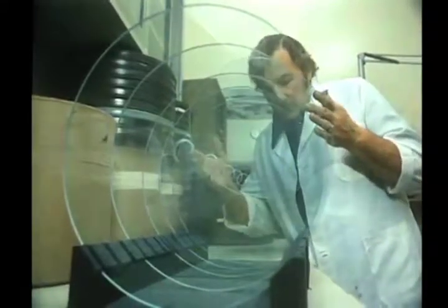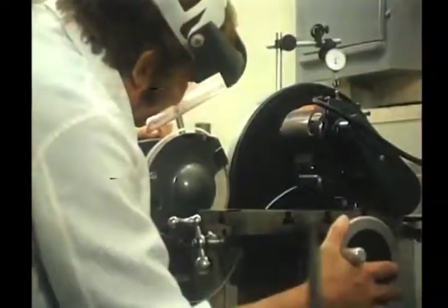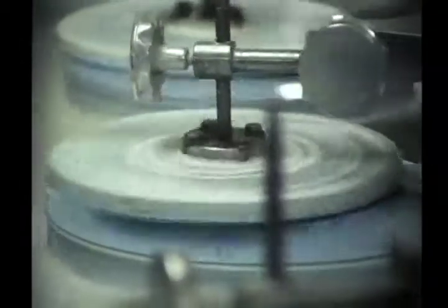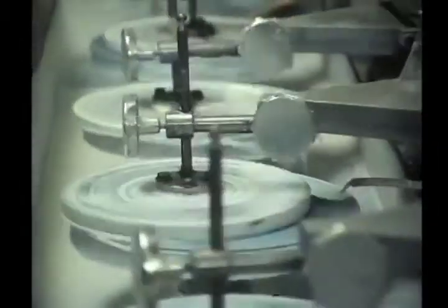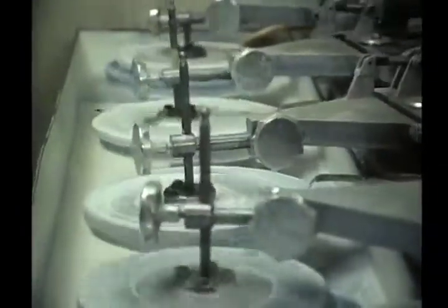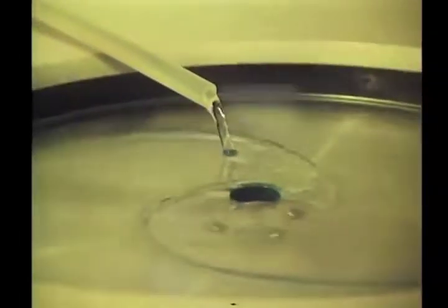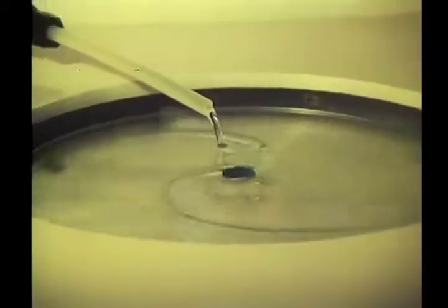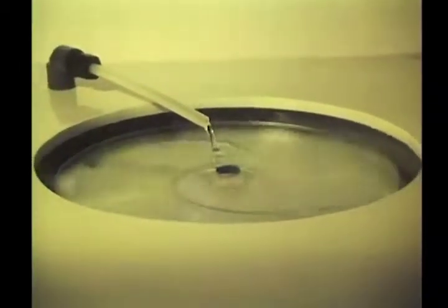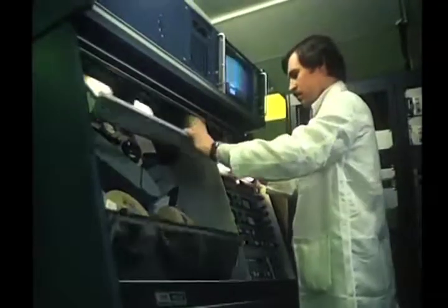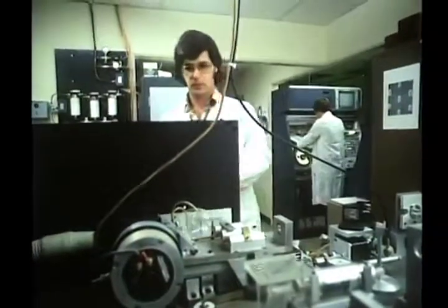The video disc you are now watching began with the production of a glass photoresist master. Chosen because of its uniformity and freedom from blemishes, the plate glass is ground and reground with extremely fine abrasive to remove all pits, then optically polished and carefully cleaned. Finally, a thin, uniform layer of positive photoresist is applied to the glass in preparation for mastering. Either videotape or film can be used as program source material, and all master recording is done in real time.